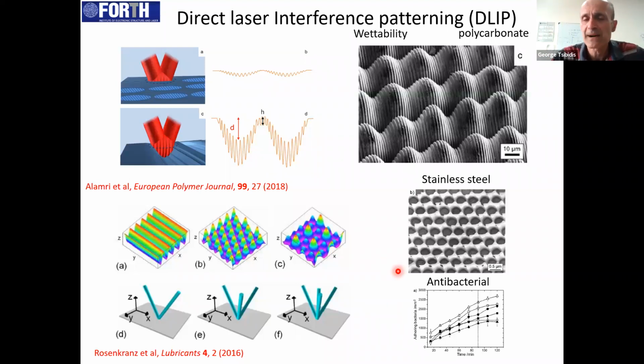So far, I have talked about the impact of Gaussian beams. So we started with a Gaussian beam. We irradiated the material, and due to the presence of defects, due to corrugation, we were able to produce these far fields, these electromagnetic waves, and the interference of the electromagnetic waves with the incident beam led to the formation of these periodic structures. The question is, what happens if we play with the beam? If, for example, we use two Gaussian beams at an angle, so at an incident angle different from zero, the interference of these two beams gives already a periodic intensity profile,